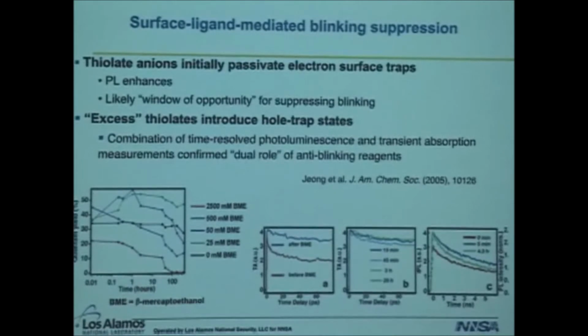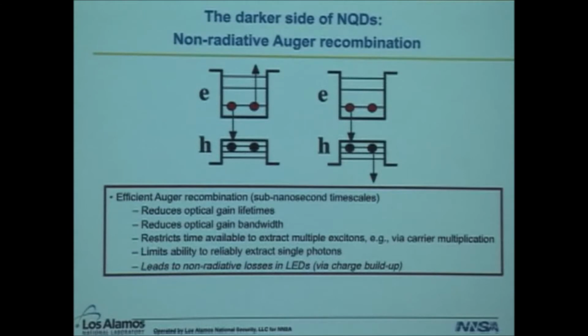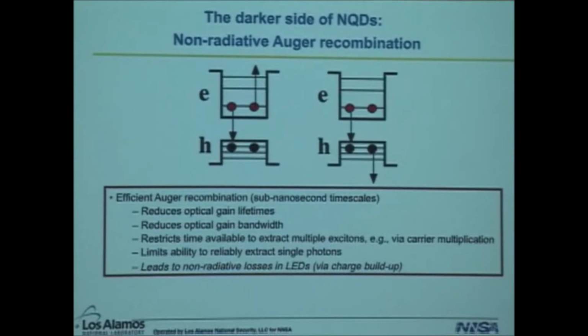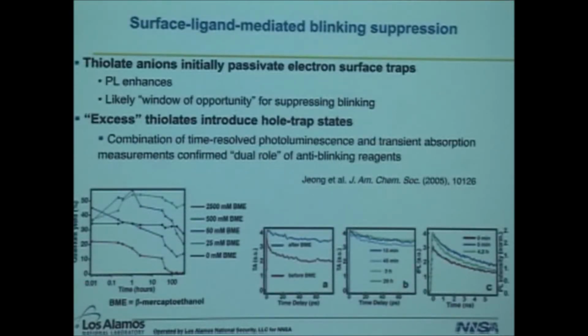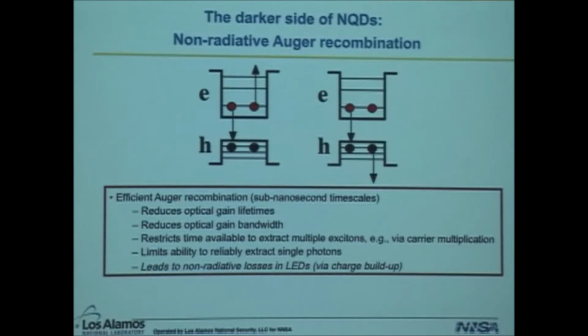And so our ultimate conclusion, based on a number of optical studies and control studies, was that this approach really fell flat with respect to applications, in that you could not rely on it, and it was just too difficult to reproduce. And so we have long sought an alternative to that approach. In addition, the ligand-based approaches did nothing to address the flip side of blinking, that being the non-radiative Auger recombination process. This fundamental photophysical attribute of quantum dots was still not altered by putting ligands on the surface of the quantum dot. And Auger, as it turns out, is an important issue